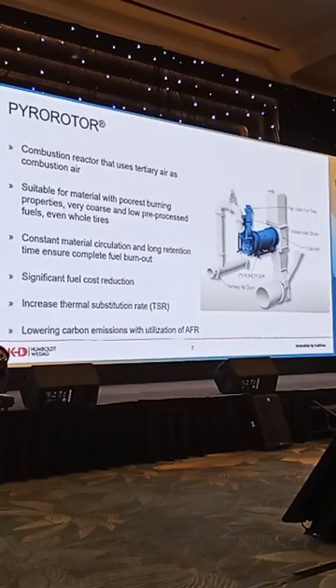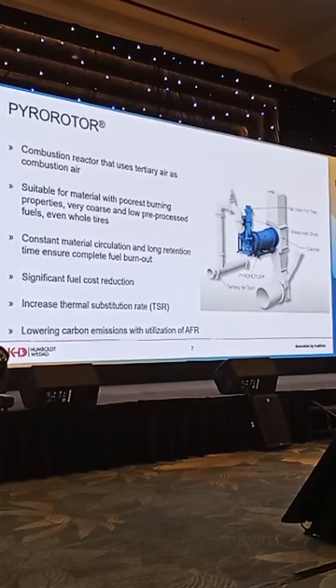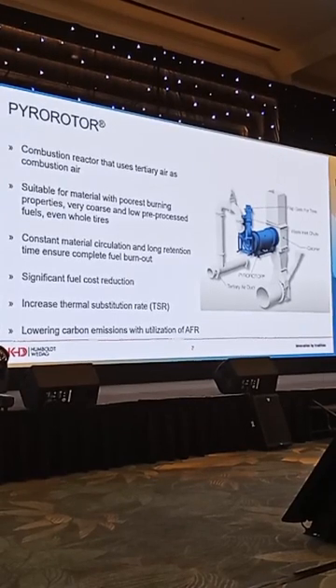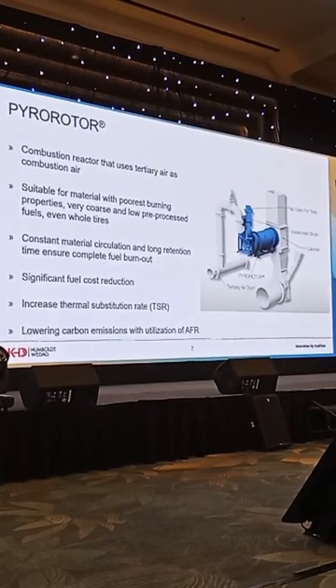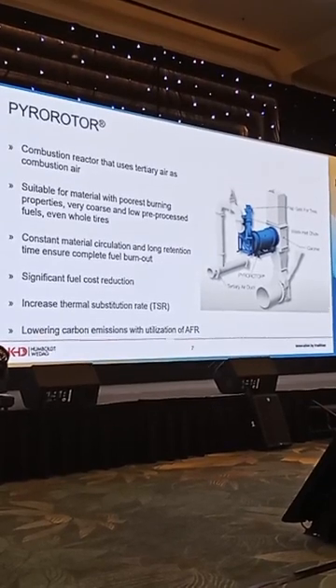What we can burn there, you can use very coarse material with really low pre-processed size, and as I already said, also by feeding whole tires. What is really important is that the fuel you want to feed there is available the whole time, for 24 hours. So you have to have a constant fuel amount, 24 hours per day, 7 days a week. So the system reacts very clearly to the amount of fuel you're feeding.